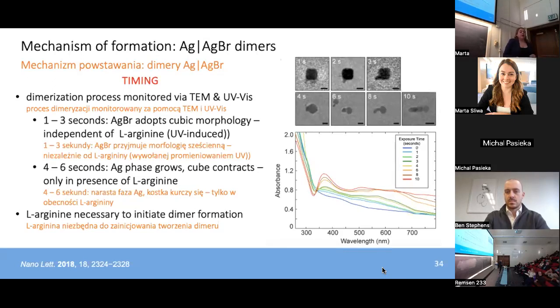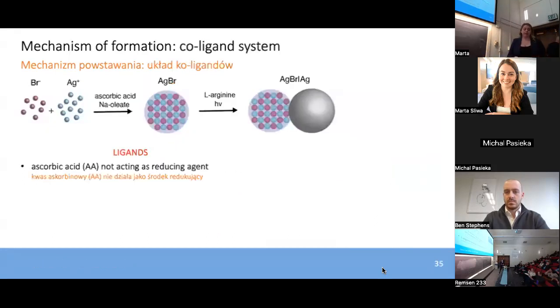These experiments also indicated that this secondary process, or that 4 to 6 second growth, is dependent on the presence of L-arginine in the system. So L-arginine is necessary to initiate that symmetry breaking process and create those silver-silver bromide dimers at the end. So having established the importance of oleate, as well as the importance of L-arginine in our system to drive the formation of those dimers, we then investigated the role of other ligands on the surface of these hosts and how they impact the synthetic process.